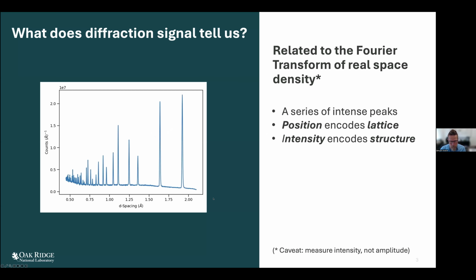So from a very basic, fundamental standpoint, what does the diffraction signal tell us? I have a picture here of a powder diffraction pattern. This is from silicon. And as you see, it's a series of intense peaks superimposed on some kind of experimental background. And these peaks encode information about atomic structure. And to simplify things, essentially the position of the peaks is talking about the lattice, the periodic unit cell, which is repeated throughout the crystal. And the intensity is telling us about the structure, the basis structure within that unit cell.